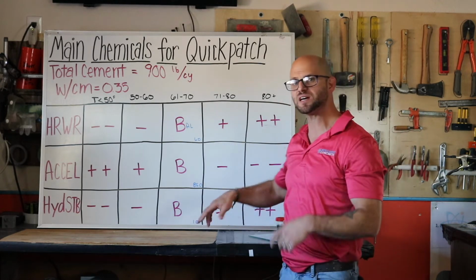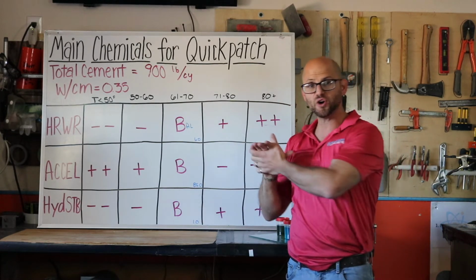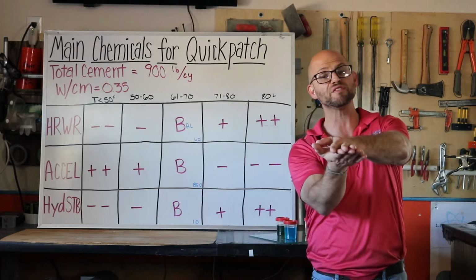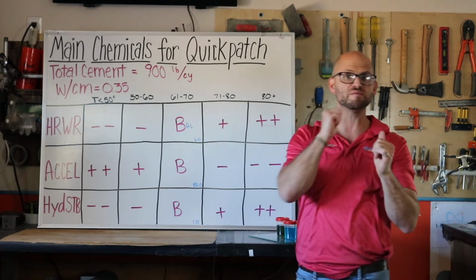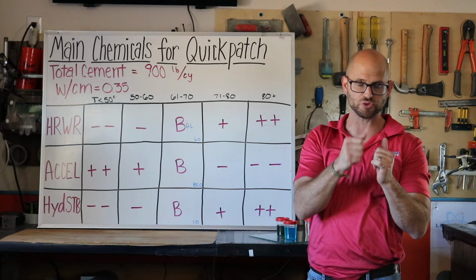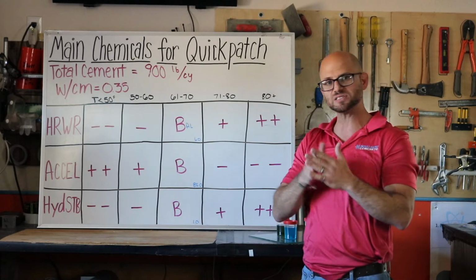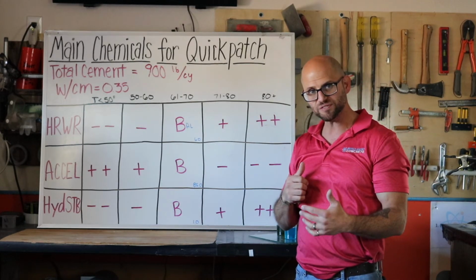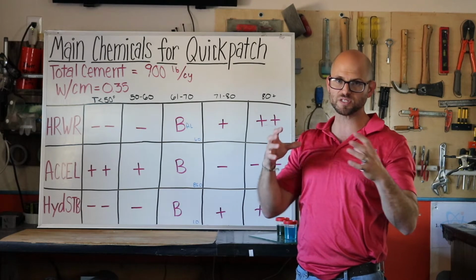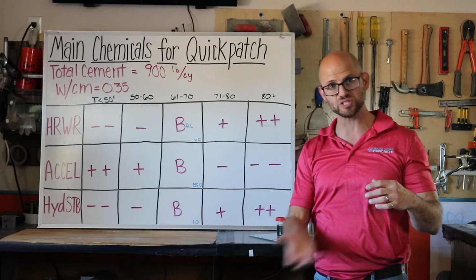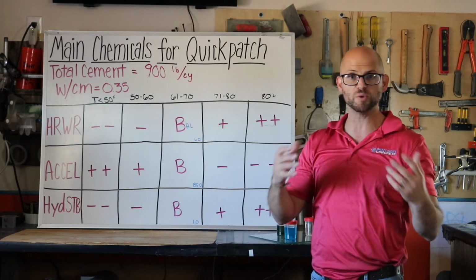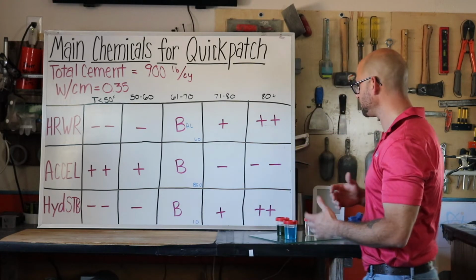I don't need as much of that salt to kick off the kinetics of cement hydration. That being said, because we've gotten hotter, the hydration kinetics want to take off, so we're going to need a half a step more of our hydration stabilizer. Again, not only to give us that slump life, but also to ensure that we're dissolving that cement, so when acceleration does take off, we've got the most potential, we're getting the most efficiency out of our cement.